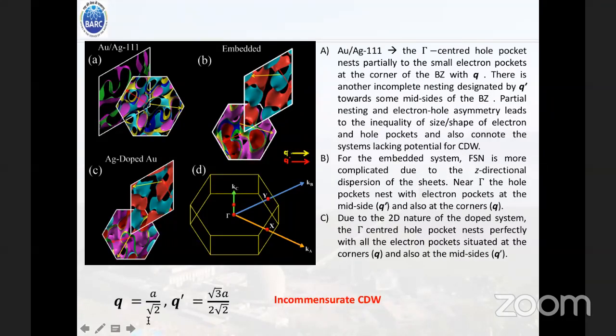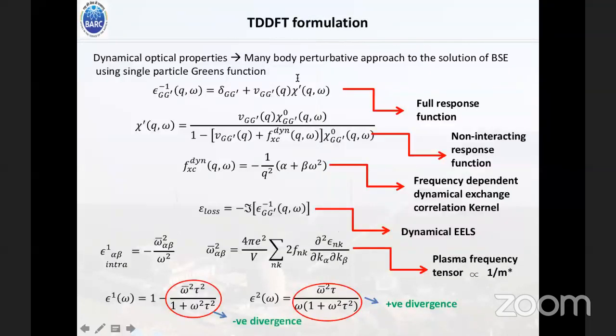If you look at the calculated nesting vectors, they are incommensurate in nature, differing from a, the lattice parameter. So these two are the potential candidates where one can have a CDW kind of instability. Next is our TDDFT formulation, where we have done a full response function, calculated from the non-interacting response function with the frequency-dependent dynamical exchange-correlation kernel.